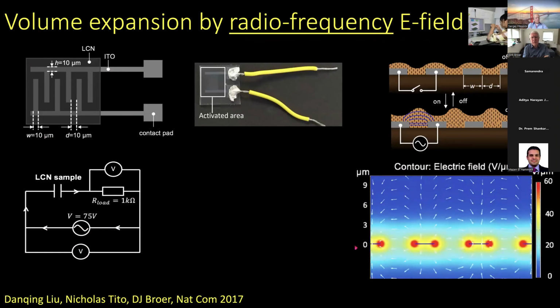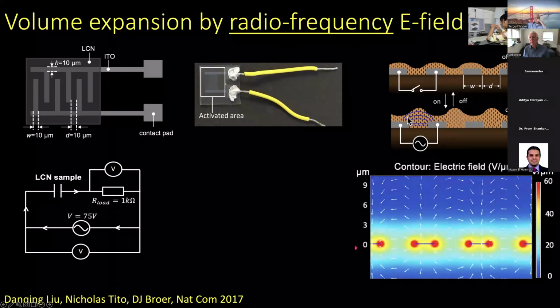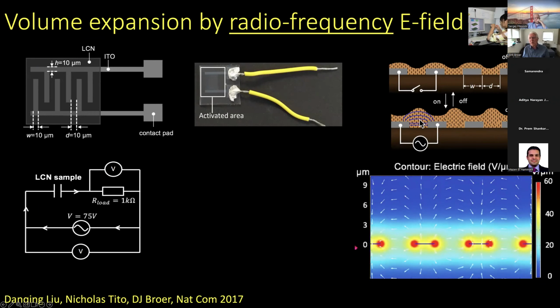So far I have discussed temperature and light mainly to actuate the surfaces, but you can also use electrical fields. And this is an example where we have the material applied on an interdigitated electrode. This is just the real sample. This is the activated area. We created a system where we have homeotropic orientation, so molecules are oriented perpendicular to the surface, and now we start actuating, and of course we hope that we will have expansion in between the surfaces, and the expansion should then be a result of the volume that we are creating.